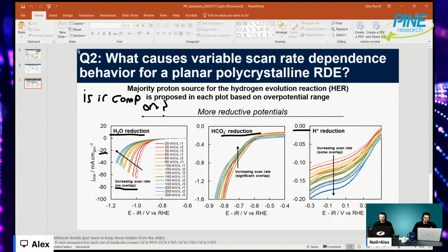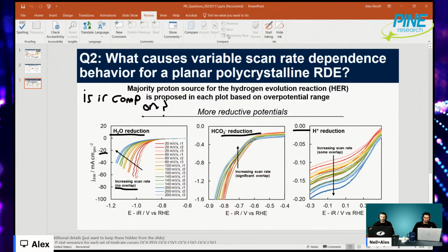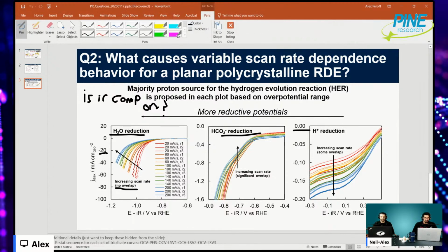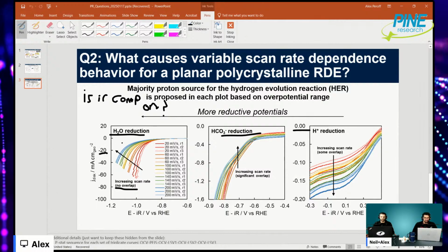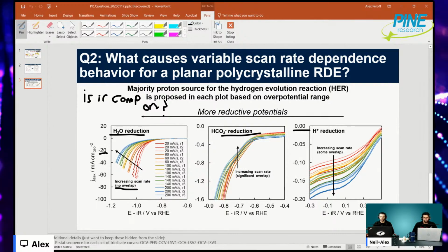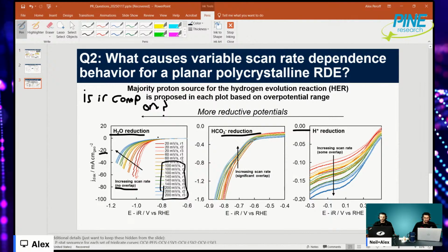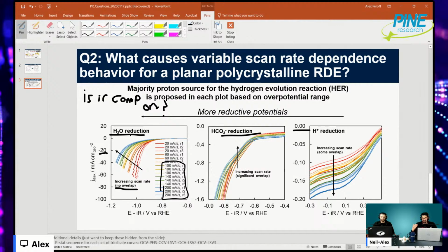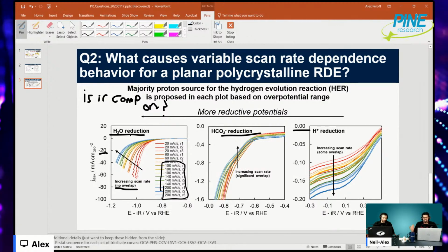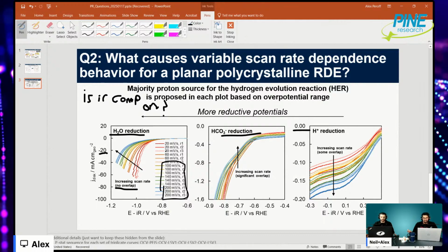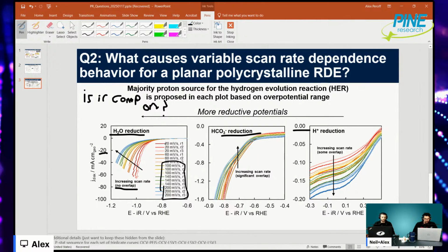Is iR comp on? So is IR compensation on is one of the big questions, because that's the main thing. That's one of the big things I'm noticing here, is that there's a shift. And this shift makes a lot of sense when you consider that when we're moving to these very high scan rates, we're pushing the potential. You're getting more current, so your IR drop is higher. So the potential where a process is occurring is much higher. And it's also noticeable if we even look at the 20.